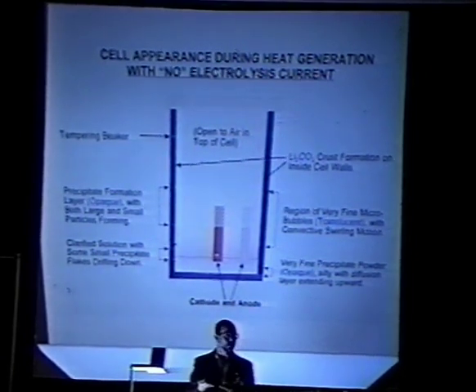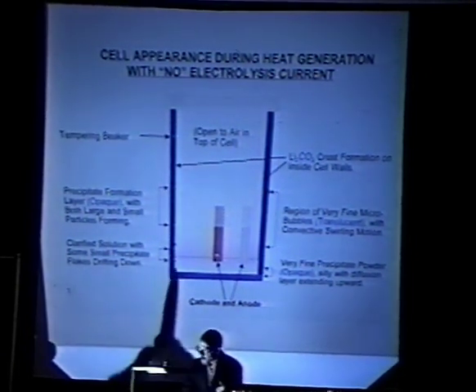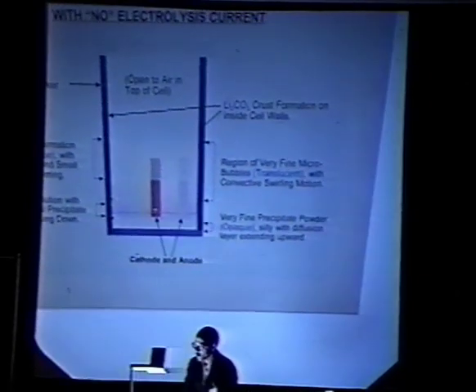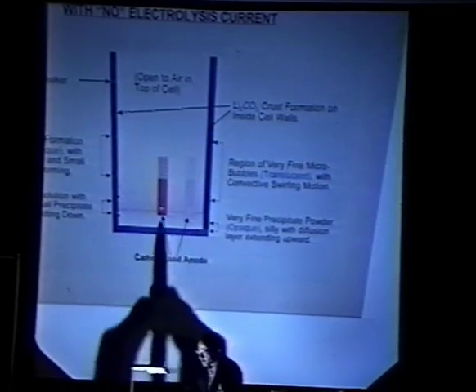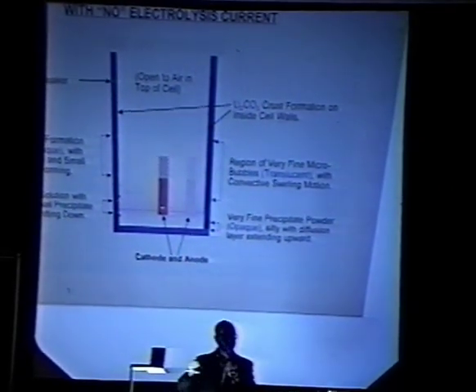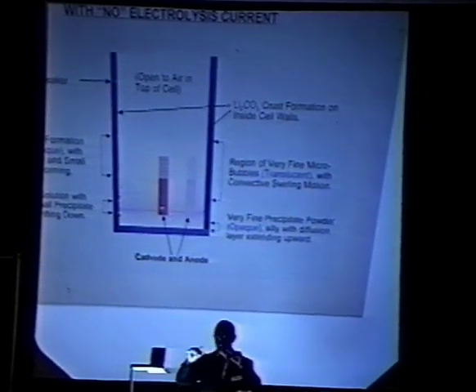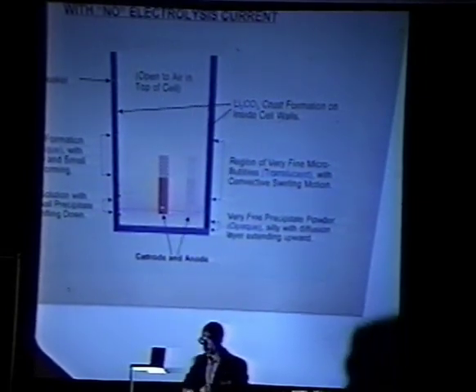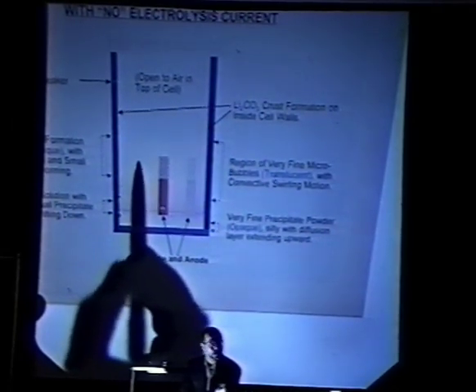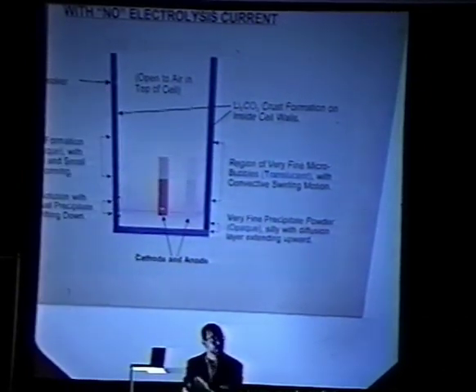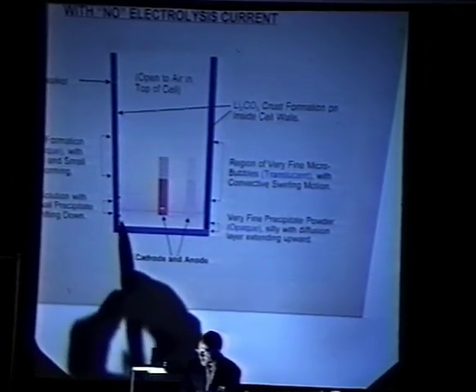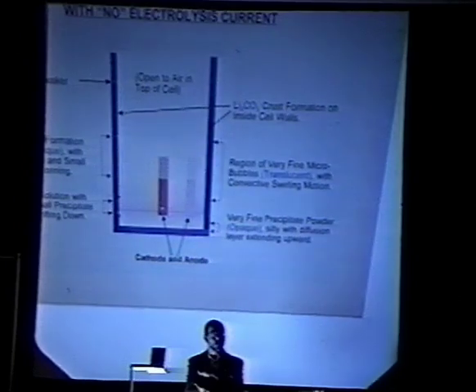It looks like it does when you're running electrolysis, with the exception of this area down here at the very bottom. I call it the very fine precipitate powder form, right here at the very bottom. Essentially it's opaque at the bottom, basically pure white, but above it is a very thin diffusion layer, where you can see this stuff appears to be dissolving and going back in solution. In fact, one of the characteristic things, staring at this hours on end, is that it appears there is some type of exchange between the carbonate being formed up here, the lithium carbonate, coming down, forming, and then somehow re-dissolving back into solution. There's a dynamic exchange going on. In fact, over hours of the run, you'll notice that this layer right in here, the thickness actually grows and then shrinks.